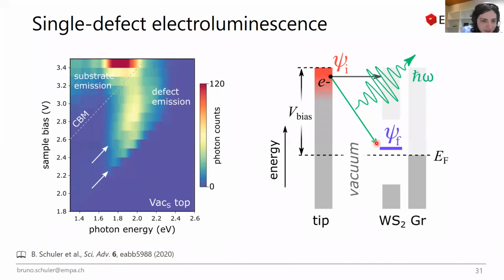There's another question in the chat by Rishabh, which is how is the RE plus doping performed? Co-evaporation during the growth of the TMD or later? It's co-evaporation. As I understood, this was not done in our group, but at Penn State. They have this vapor transport mechanism in this MOCVD, and by mass flow controllers, they can dose different amounts of this precursor vapor into the cells. So they have a very controlled amount of precursor that they can deposit during the growth, bottom up.